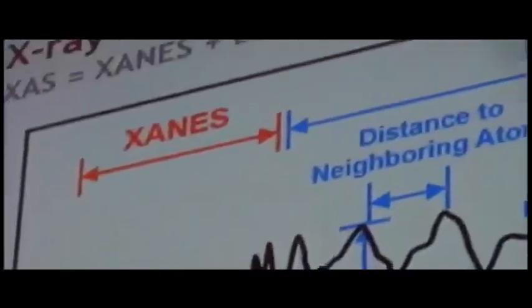That third component is what we're mostly interested in a XANES experiment, monitoring how the oxidation state of the metal is changed. The little wiggly lines off to the far right there is what's called the XAFS portion, EXAFS, which tells the type of the neighboring atoms, the ligands that are associated with it, the distance to those various atoms, and then finally the number of the neighboring atoms that we have. So with a single XAS experiment, which is the combination of XANES and XAFS, we can gain an incredible amount of knowledge about the material. We've worked over a number of years to develop cells and techniques to really work on these catalysts under realistic conditions, high temperature, high pressures, and reacting gases. And we use it extensively there.